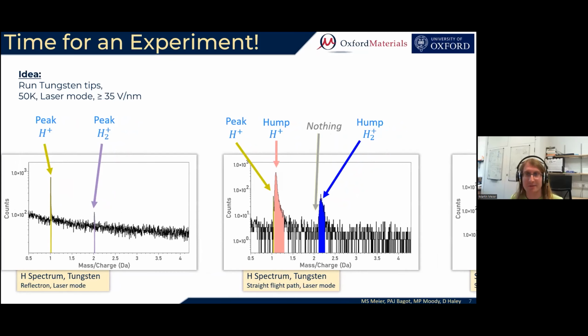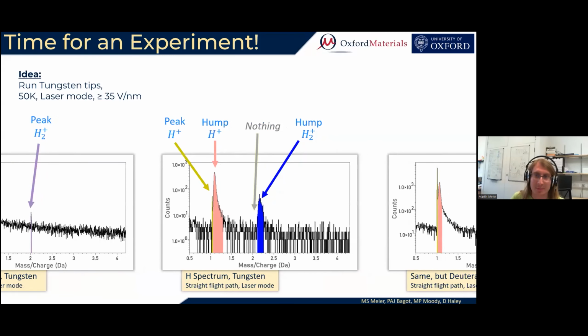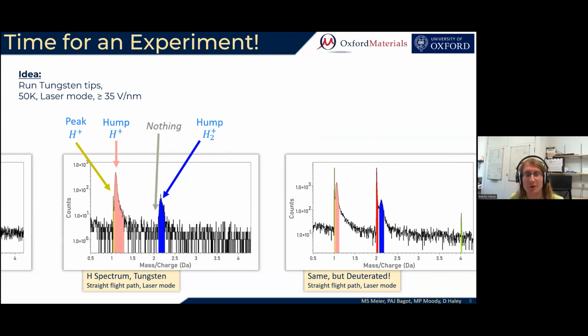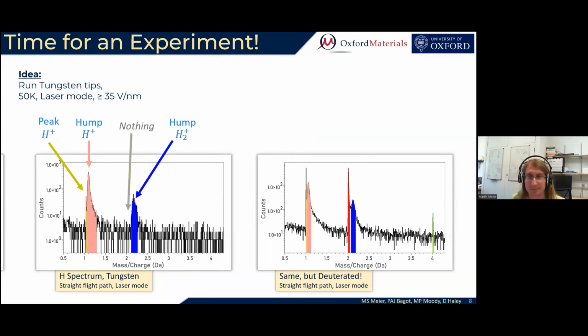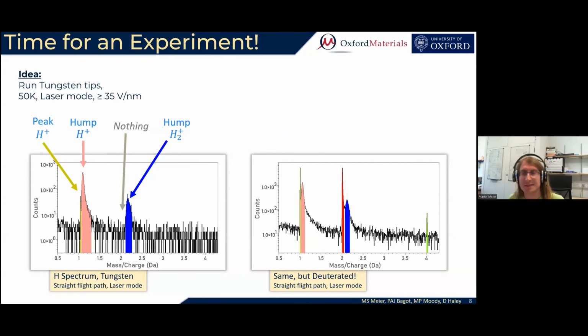A third experiment that we can then stack on top of this is another repetition of that entire thing, but this time on a deuterated tip in a straight flight path machine. And deuterium is a hydrogen isotope that's naturally very rare, and that's twice as heavy as the naturally abundant light hydrogen. And what we see in here is this: the mass charge 2 peak is now back, and that's because of deuterium.